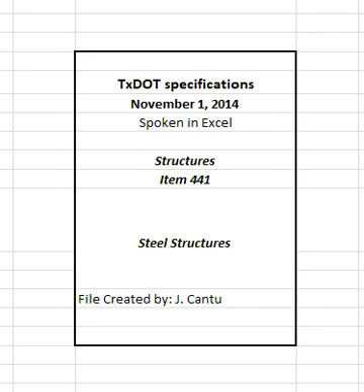3.2.2.2 Grinding splice welds. Grind shop groove welds in flange plates smooth and flush with the base metal on all surfaces whether the joined parts are of equal or unequal thickness. Grind so the finished grinding marks run in the direction of stress, and keep the metal below the blue brittle range, below 350 degrees Fahrenheit.